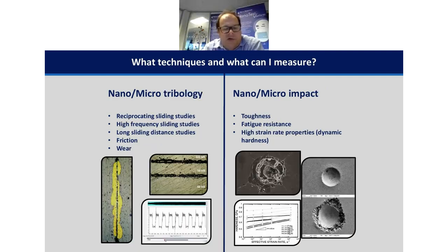We have some other tribology techniques as well, which bridge the gap between scratch testing, which is a single contact high pressure loading test, and what we might regard as traditional tribology work with things like pin on disc tribometers. So we have some reciprocating sliding tests at different scales. We have nano fretting, and a device called nano tribo test, which allows us to do reciprocating sliding up to tens of millimeters sliding distance. Again, we can study friction and wear with these techniques. So we have different tribology techniques for different scales of interest.